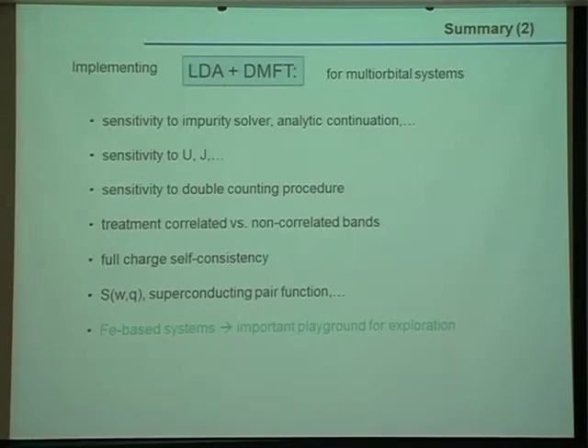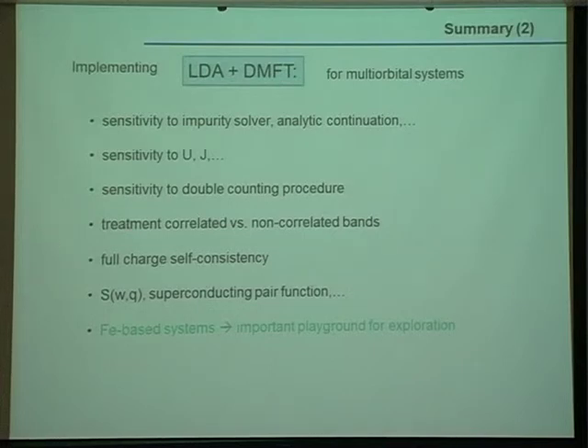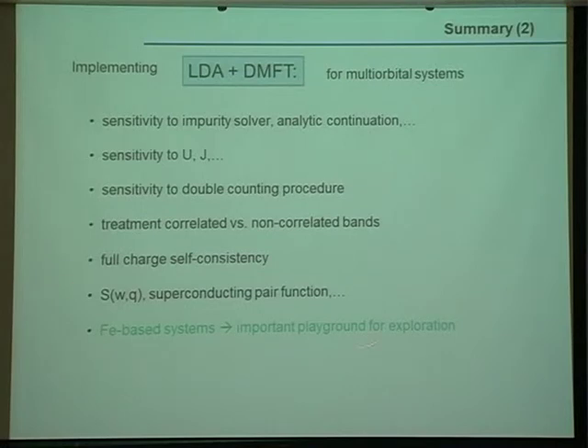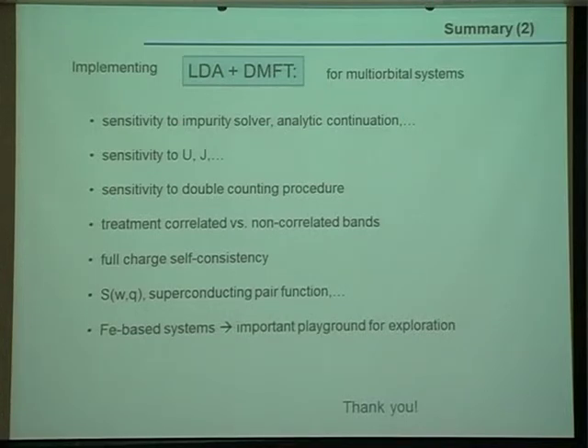There is a large sensitivity on the values of the interaction parameters that enter the calculation. One should also be careful about the double-counting procedure, how to treat correlated versus non-correlated bands, and doing full charge self-consistency. It would be very interesting to explore other properties beyond spectral functions. These materials are an important playground for exploration. Thank you for your attention.